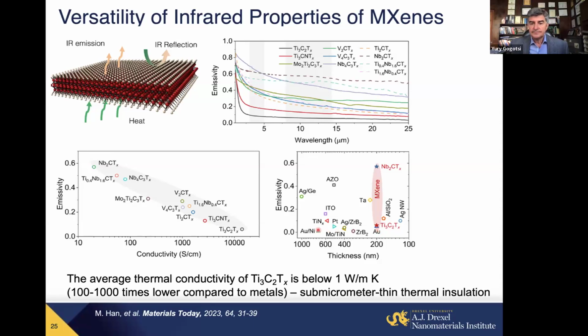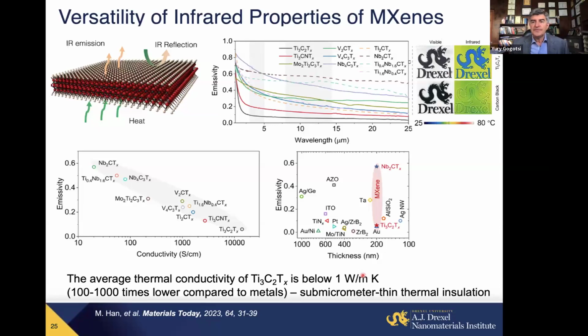All the metals have thermal conductivity like 100 to 300 watts per meter Kelvin. The titanium carbide MXene film I showed to you, like a micron thick film, has conductivity less than 1 watt per meter Kelvin. So if you want to do heat shielding, it will be at least 100 times better than reflective metal foils or coatings in a window. You can see the Drexel logo, the Drexel Dragon, stays cool, blue, after being put on a hot plate. And this is like a 200 nanometer film.